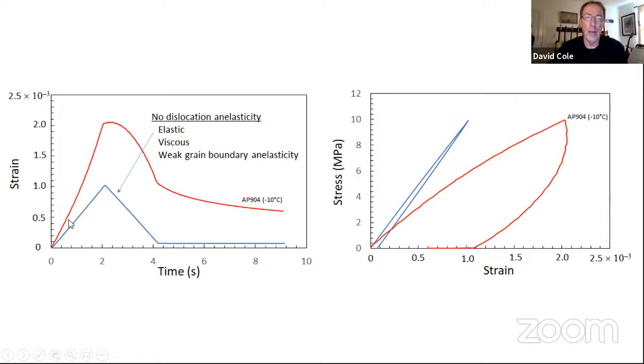So if you had no dislocations in your life, and we're trying to model this with an elastic process and a viscous, let's say, or damage process that would allow some permanent strain. There's a weak grain boundary relaxation. We won't worry about that too much. It's a lot faster than our load application, so it looks like it's in phase. It just looks like a slight decrease in the modulus. But I wanted to just leave that in there.